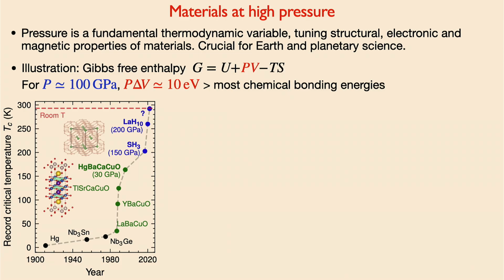Then there was a real breakthrough with the discovery of superconductivity in cuprate materials. Cuprates are ceramics. They are dirty materials. Bednorz and Müller found that LaBaCuO was a superconductor with a great increase of the critical temperature. That was, of course, a very surprising discovery. No one was expecting superconductivity in such dirty materials. It's called unconventional superconductivity, meaning that you don't understand what's happening. That's not exactly true now, there have been a lot of studies, but after almost 40 years we still do not understand the physical reason that makes those materials superconducting.